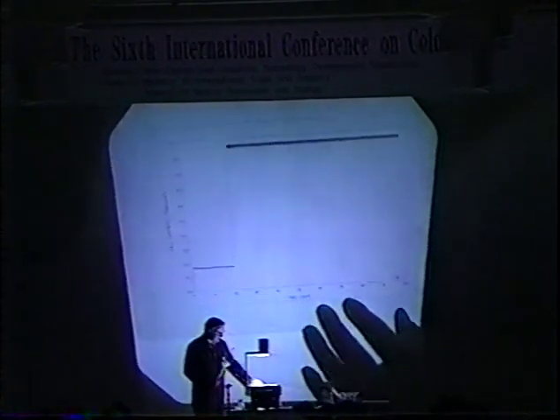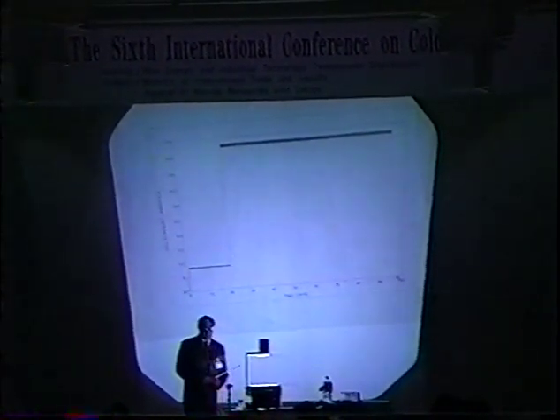So a typical protocol for making a set of measurements is to apply constant current. We do control power and control voltage experiments as well, but a typical experiment is maintaining a current density of somewhere between 20 and 100 milliamps for an extended period of time. This is a very low power experiment, as it turns out, but basically the protocol is the